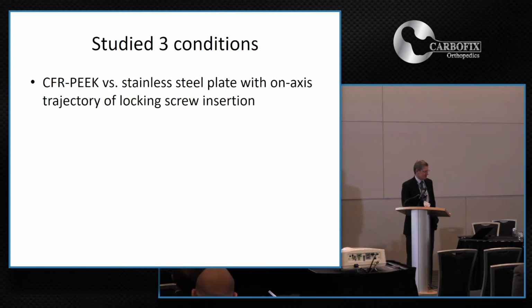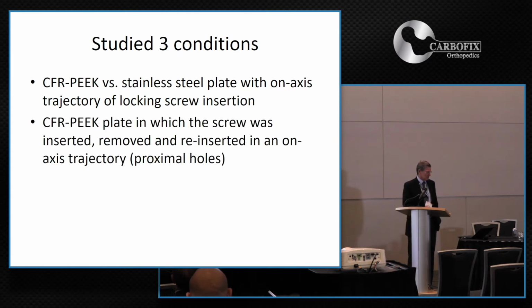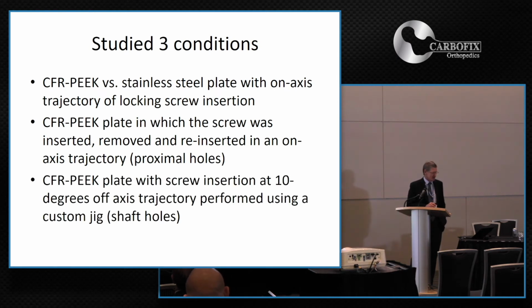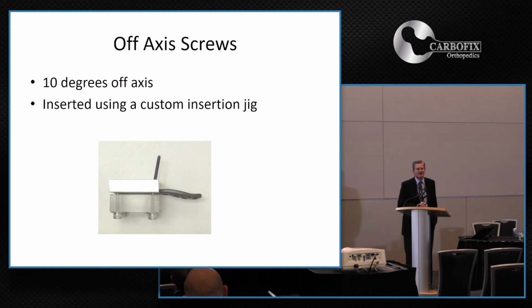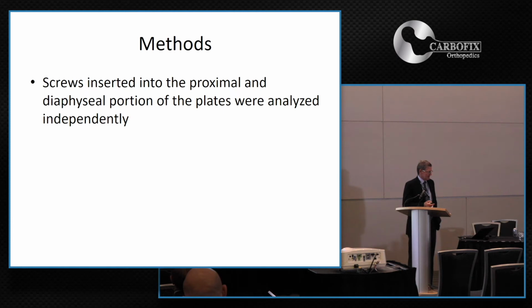And we studied 3 different conditions: the plate with the on-axis trajectory, with a screw after being removed and then reinserted on an on-axis trajectory, and then the insertion of a screw that was 10 degrees off the axis. And we used a custom jig in order to put that screw in on that 10-degree off axis. And we inserted screws both into the proximal aspect of the plate and into the shaft portion and analyzed those independently.